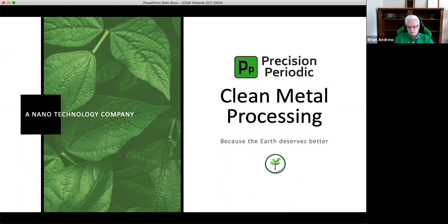What we found is if you go to the dirt now and leach the dirt, not with a specific leach like a cyanide, but with a non-specific leach, in this case a chlorination technique, say hypochlorous acid on the ore, the gold comes out in seconds, the silver comes out in a few more seconds. You get a lot of iron, you might get a lot of cobalt and copper, but that's okay, that doesn't matter. You can get out 100,000 parts per million iron, it doesn't really bother us, it just costs you chemistry. So you do a very fast leach, separate your dirt from your leach really quickly, about 5 minutes for a filter press, and now you've got a chlorinated liquor.